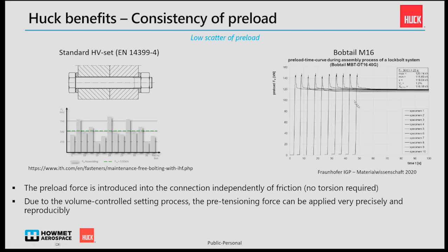On the right-hand side, we see some installation tests of an M16 Bobtail. The diagram shows the preload on the y-axis and the time scale on the x-axis, and we see that the resulting preload is a very constant value. For this example, only a mean value of 116 kilonewtons and a scatter of 1.2% between these 10 tests. And this is due to the constant material properties of the collar and also of the installation procedure by swaging the material into the lock grooves.